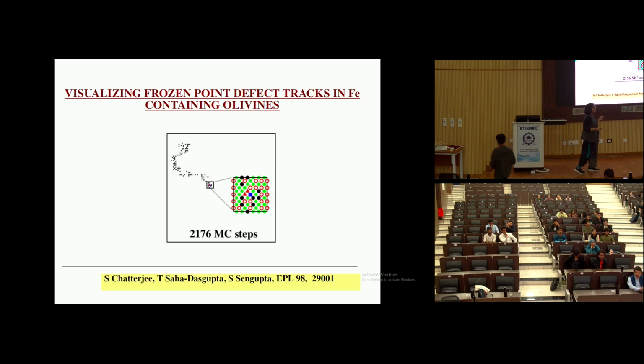So now all of these, where you assume your mineral is perfect, but it's actually not perfect, especially when all these minerals are formed. Depending on their formation condition, you actually have some vacancies, missing sites. And depending on which condition the mineral is formed, there can be plenty of vacancies. Any naturally forming mineral will have those vacancies. Now, these vacancies become mobile, right? They will move from one site to another. There will be a diffusion of those vacancies. So how do they really change the properties?